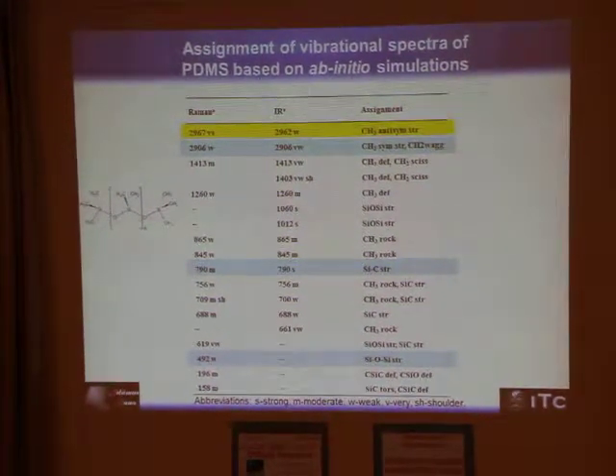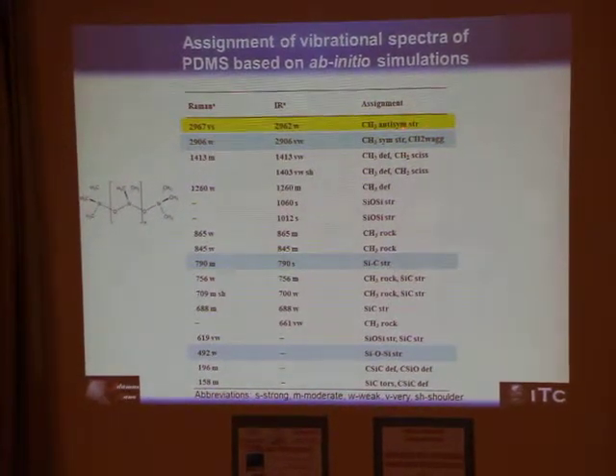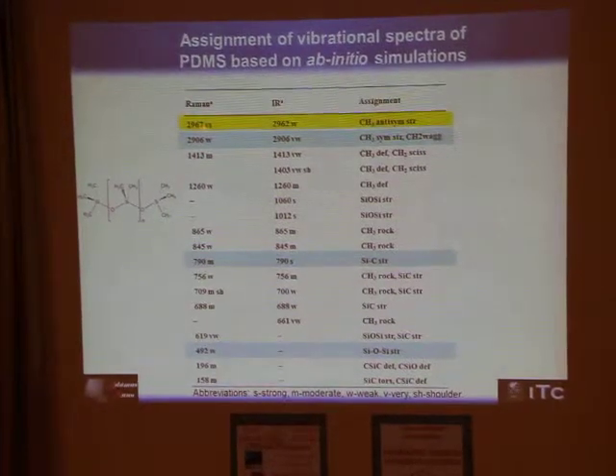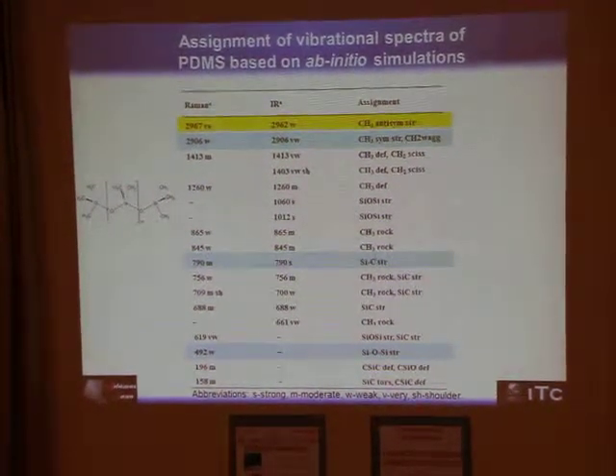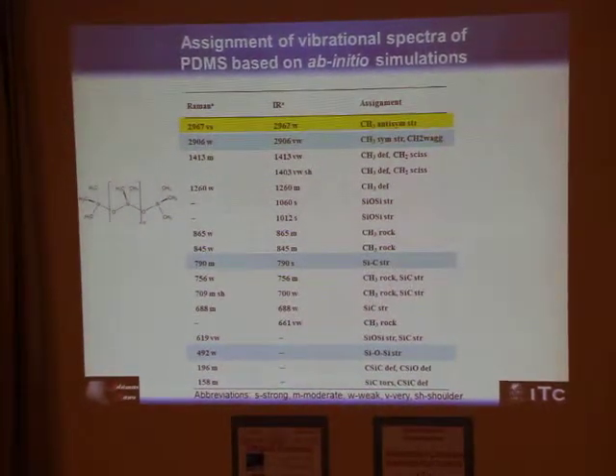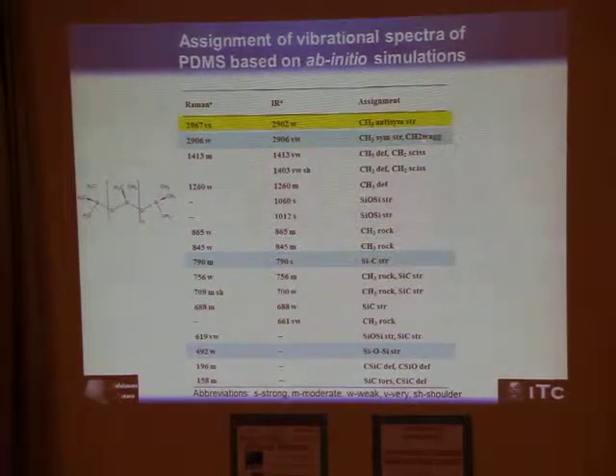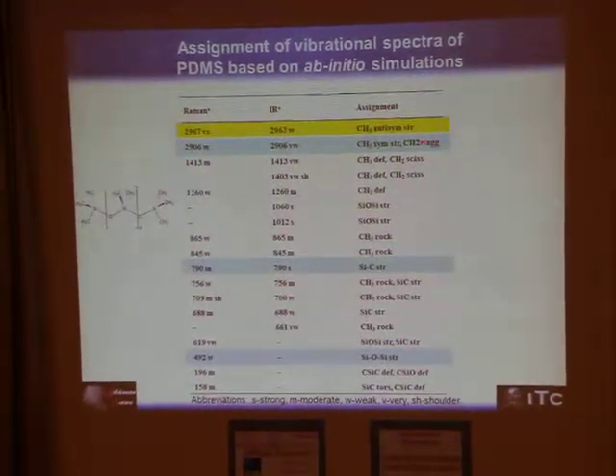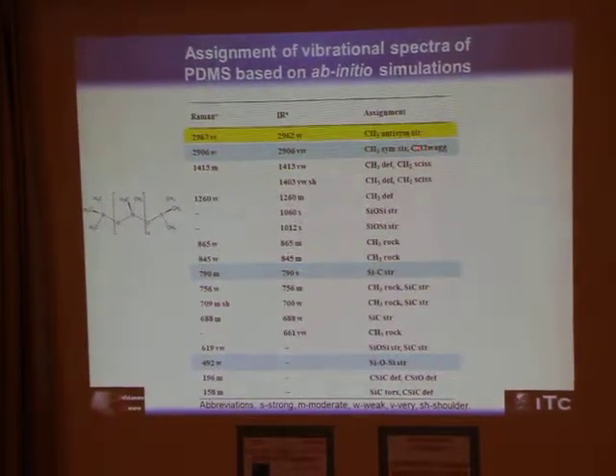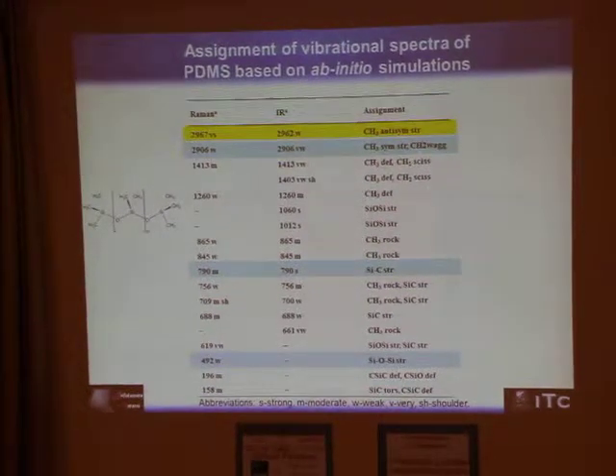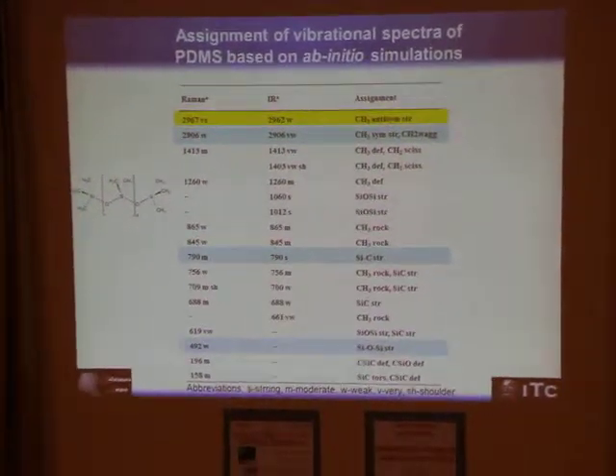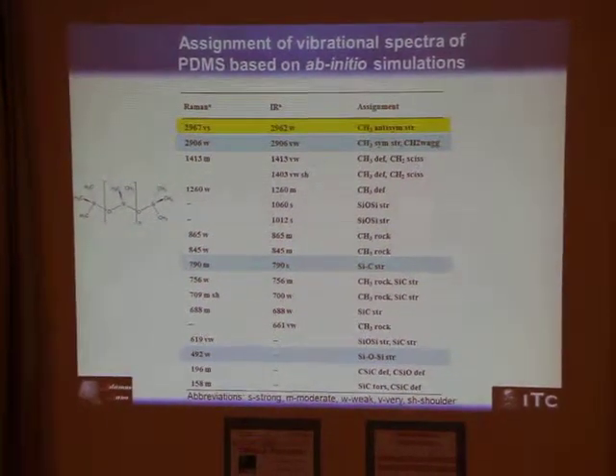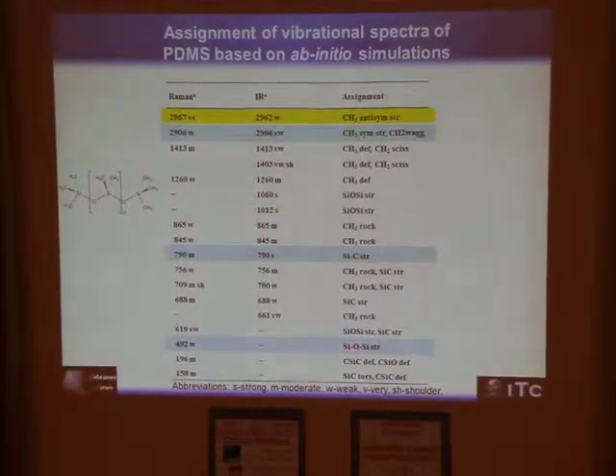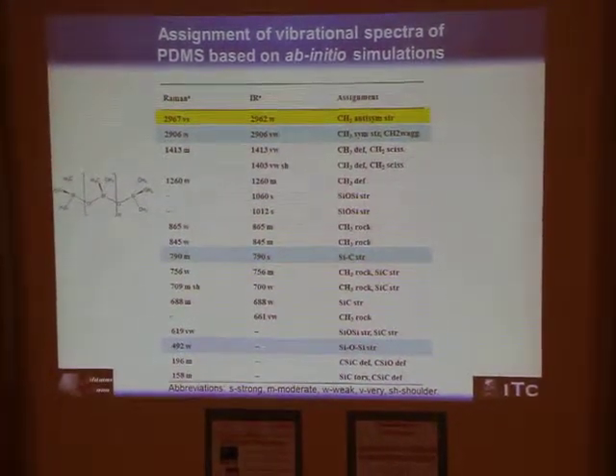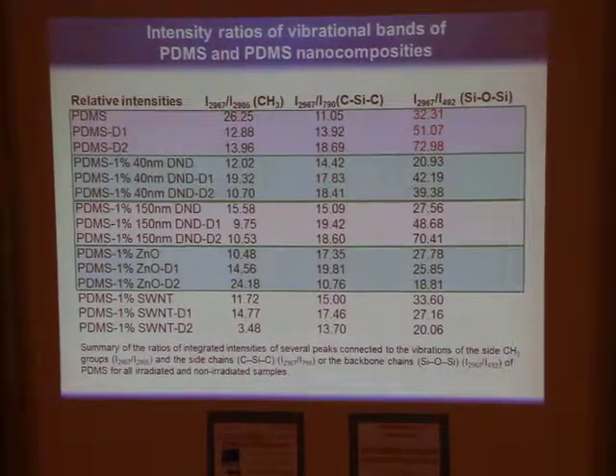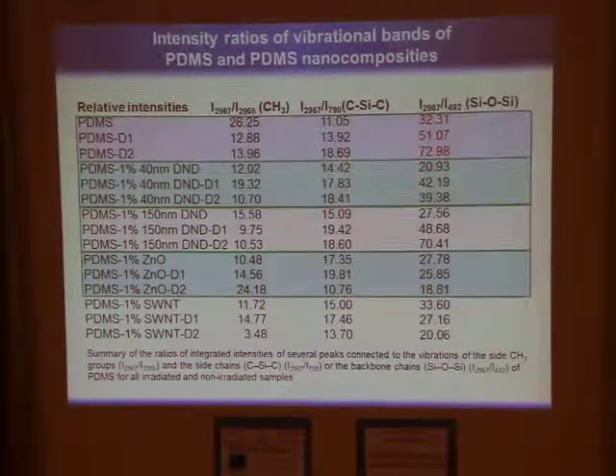And what the colleagues also did, they took the intensity of CH3, the strongest antisymmetric stretching peak, and calculated the ratio of intensities of this peak and some other characteristic peaks attributed to CH3 vibrations, such as CH3 symmetric stretch. It also contains the CH2 wagging mode, the silicon-carbon stretching mode and the silicon-oxygen stretching mode. So this table contains these ratios of integrated intensities of these characteristic peaks.